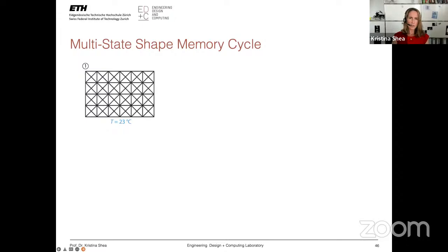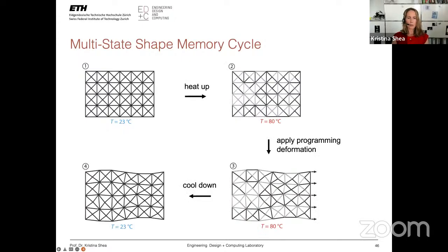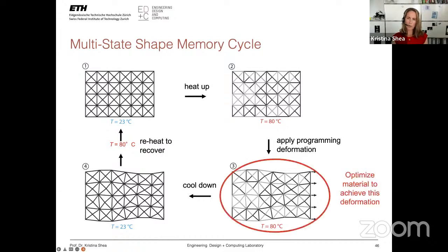So this creates a different type of programming cycle. So we have a lattice structure. We heat it up, in this case to 80 degrees. We apply the load, and then we get the deformation depending on the distribution of the materials in the structure. We cool it down, it locks that into place, and to recover back to the initial state, we heat it back up again. So you still get this programming cycle, but you don't have to program individual members. So you program it all together.